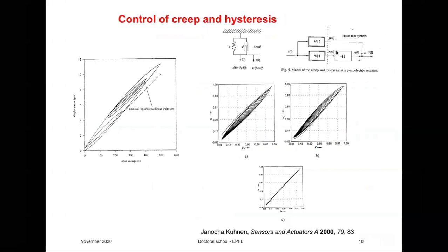Also in this section, you remember that we said that in ferroelectric materials we will have this hysteresis, and the hysteresis is not good for applications because basically what it gives us is two different states for a given field. So if this is a field, you have response R1 and R2 for the same field, or you have that for the same response, you can achieve with two different forces. And this ambiguity, this hysteretic behavior, is not something that you want in a device.